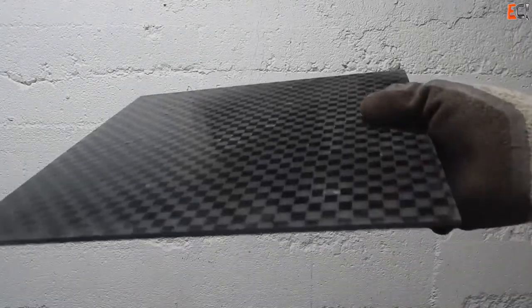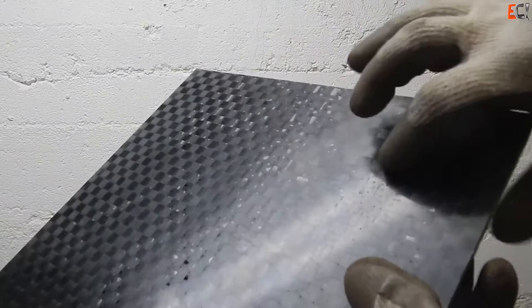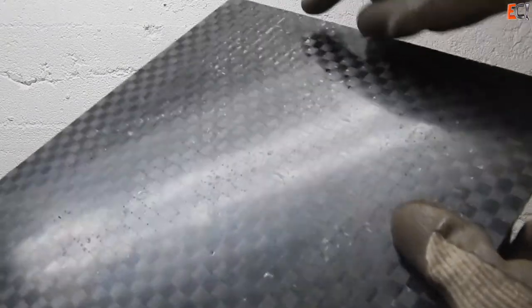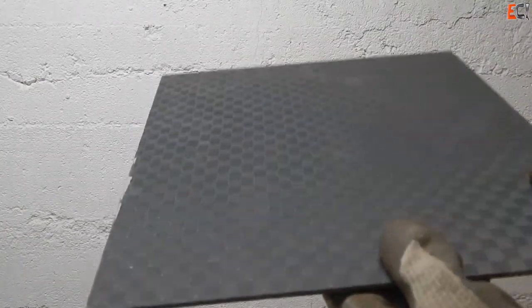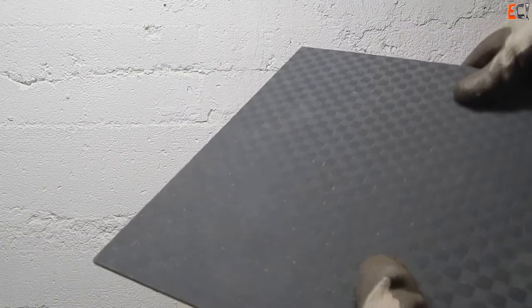Here's the panel, just to look at it, you can see the air in that surface. And there really was nowhere for it to go. And there's quite a bit of excess resin in this bottom skin because it couldn't bleed anywhere. And around the perimeter of the panel where the resin could bleed out to the periphery, there was a much nicer surface.